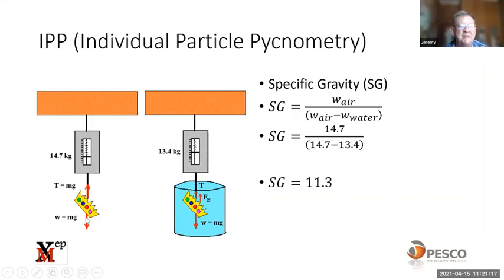So if we look at this, if you weigh the crown in air, this is example 14.7. When you submerge the crown in water, the weight is 13.4 kilograms. And then using this formula, we can calculate specific gravity, which is the weight in air divided by the difference between the weight in the air and the water. So 14.7 is the air, and then 14.7 minus 13.4 is the difference, and you get 11.3. And therefore, it wasn't gold, because pure gold has a density of around about 19. But that's the principle that we use for analyzing individual particles.